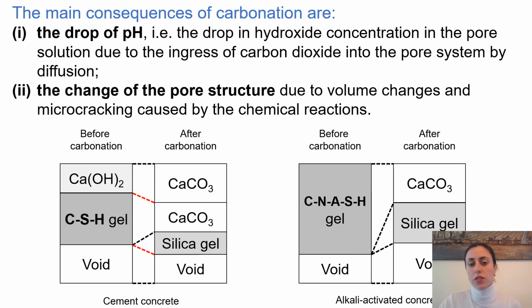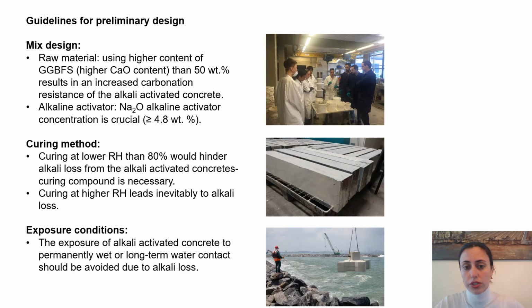So the main consequences of carbonation between cement and alkali activated concrete are drop of pH and the change of the pore structure, which is actually occurring for alkali activated concrete much faster because they have a lower calcium oxide content. Some guidelines for preliminary design for concrete where it would be exposed to carbonation.